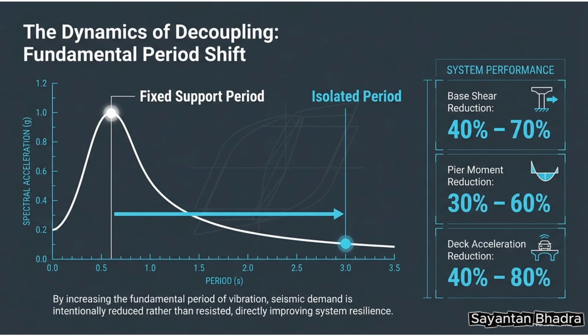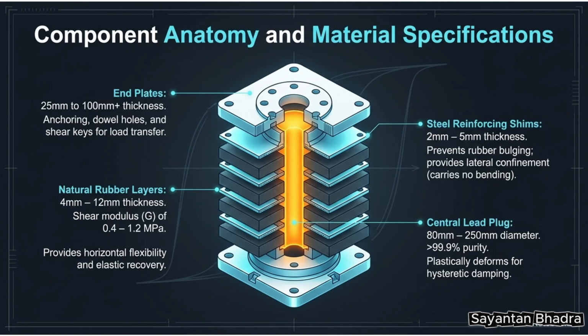Integrating an LRB lengthens the structural fundamental period from a stiff range around 0.6 seconds out to an isolated period near 3 seconds. This period shift moves the structural response down the spectral acceleration capacity curve, achieving a 40% to 70% reduction in base shear demand, a 30% to 60% reduction in pier overturning moment, and up to an 80% reduction in deck acceleration.